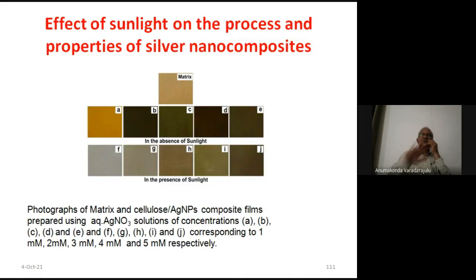Then, because it takes at least 24 hours for making the nanocomposite in the laboratory, we thought, especially for silver, because it is photochemical, why don't we reduce the time by carrying out this entire process in sunlight? So we already prepared these films in the laboratory for 24 hours, and then we carried out the same experiment in the presence of sunlight. Within 2 hours, we could get these films in the presence of the sun. This is the absence of sunlight, and this is the presence of sunlight. This is the matrix here.